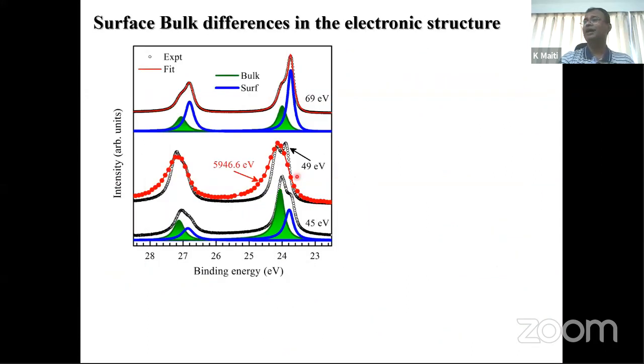Okay. Now, instead of hard X-ray, let's use soft X-ray, or say extreme ultraviolet region. There you see the same peak. This is bismuth 5d, and you can see that this 4f 7/2 peak shows a two peak structure instead of the one peak that was seen in hard X-ray. Since hard X-ray is bulk sensitive and it matches with this peak, we can think this is probably the bulk peak, and there is a clear surface peak which becomes visible only when you go to low energy, where your probing depth is of the order of, say, 6 angstrom or so. So that means that in this material, the surface electronic structure, if it is different, is actually confined close to the surface, like one or two layers.